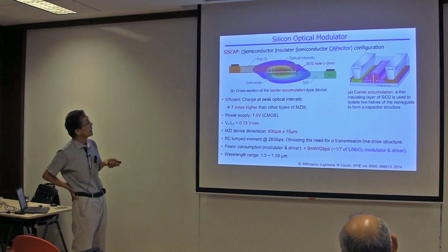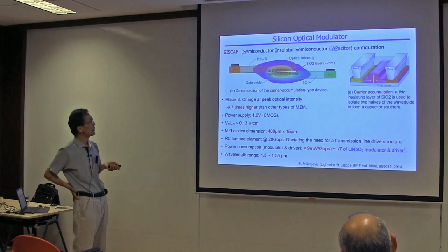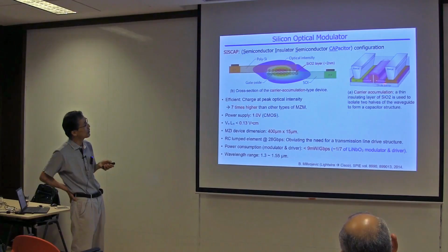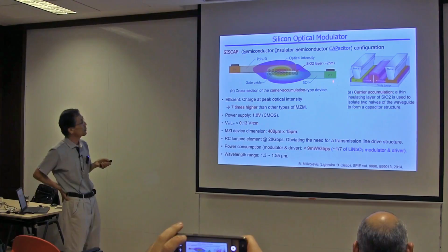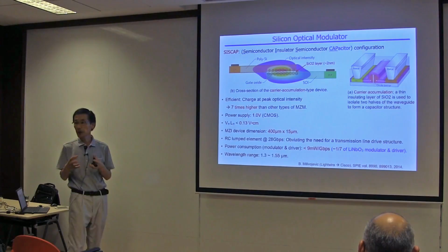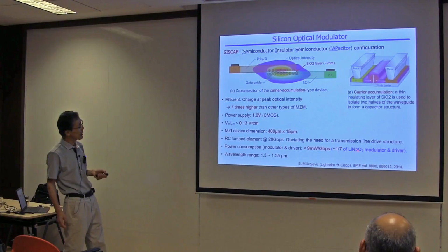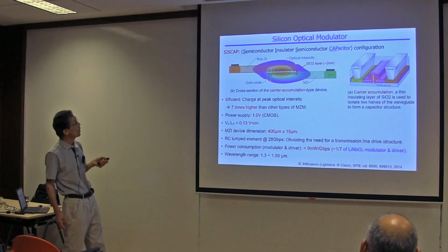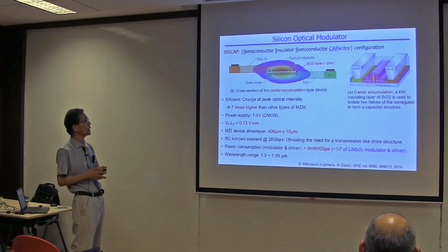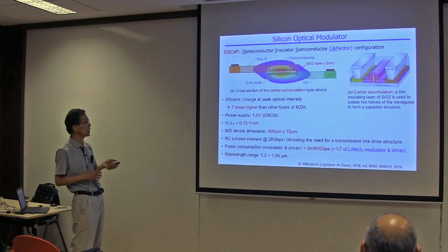The greatest advantage of silicon material is quite low cost. Cheap modulators are available. Here people use this PIN configuration, and carrier accumulation type modulation has been almost commercialized. The interaction between the carrier and optical field can be intensified and is better than current lithium niobate based modulators. So active operation in silicon is quite advantageous compared to indium phosphide modulators, because indium phosphide crystal is a niche material and quite expensive compared to the silicon industry. So this modulator is definitely an advantage of silicon photonics.